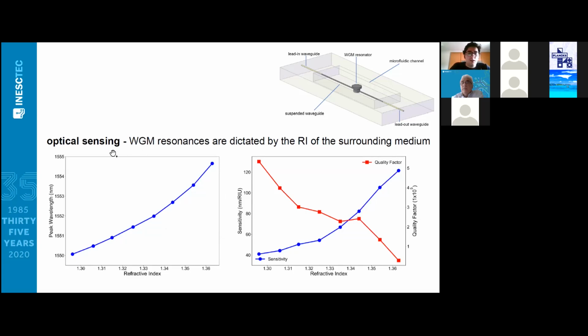This sensing arises from the fact that the wavelength of the excited whispering gallery mode resonance depends on the index contrast between the disk and its surrounding. So this will dictate the effective refractive index of the excited modes. And as you can see here, we can monitor changes in the refractive index by monitoring the shift in the peak wavelength. And as you can see here in the curve in red, we have a high quality factor around 100,000 throughout a very wide refractive index range.